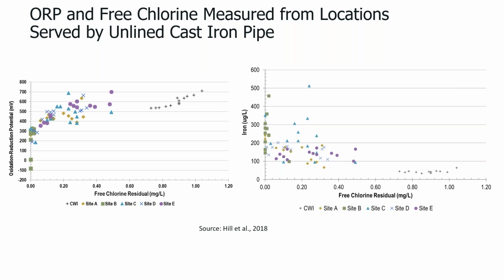This is the good fresh water coming into the system when we can see chlorine is good and high, ORP is good and high. And then we have sites moving farther away and maybe into dead ends or pressure zone boundaries into the system where we're losing our free chlorine, and we can see, especially in these green bars against unlined cast iron pipe, we lose the chlorine, we start releasing iron, it chews up any remaining chlorine, chews up dissolved oxygen. We can get low to negative ORPs out in the distribution system.